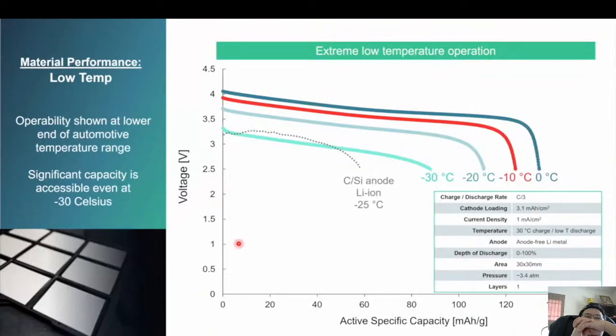So next, temperature performance. One of the knocks against a solid state battery is that they have to be hot to run. I think maybe that intuition might come from polymer cells that need to be heated to 60 or 80 degrees to have sufficient lithium ion conductivity. So we wanted to show that our materials are capable of running across the full automotive temperature range down to minus 30 degrees C. This just shows a single C/3 discharge at decreasing temperatures from 0 degrees down to minus 30 degrees C. In between each of these discharges, we would do a C/3 charge at 30 degrees just to get the full charge capacity.